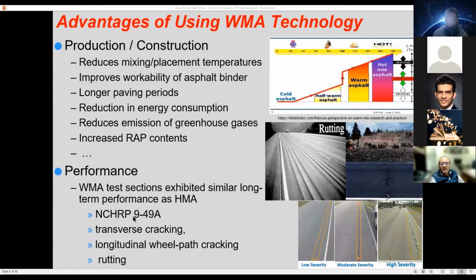So the advantages of using WMA additives are listed in here, and basically it allows you to reduce the mixing and placement temperature. What that basically means is that it can improve the workability of the asphalt binder, and also you can establish a longer paving period. It can reduce energy consumption. It can participate in the reduction of emission of greenhouse gases. And from a material standpoint, it can allow you to use an increased RAP content. And you can see that all these things can be incorporated into the development of a framework for sustainable development.